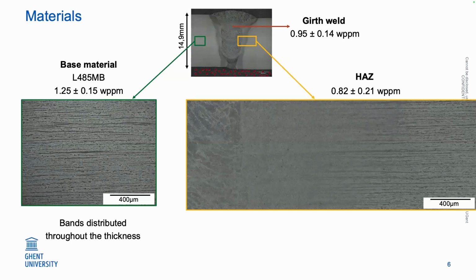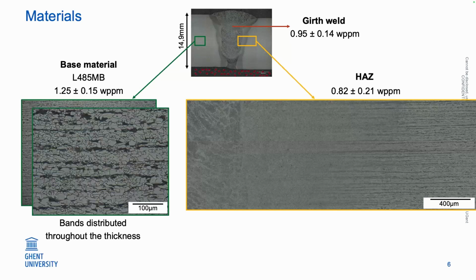The pipeline material is L485 steel, which is similar to an X70 steel. What do we see in this material? We see hard bands distributed through the thickness. Those dark bands contain pearlite, but also hard inclusions.